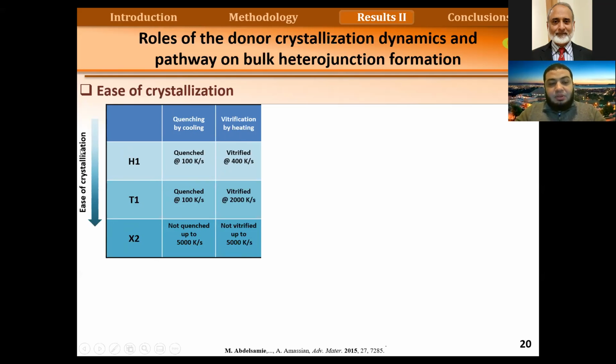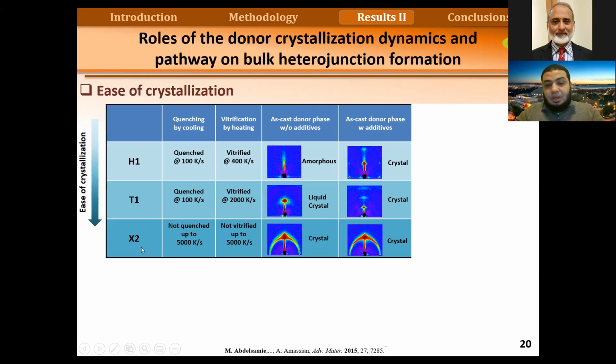We can see on the left here that the ease of crystallization changes from H1 to T1 to X2. When we make a film, for H1, because it can be vitrified very easily, it forms an amorphous compound without additives. The second one forms a weakly ordered liquid crystalline phase, and the third one forms a crystalline phase without additives. If we use additives, we can form a crystalline phase for all of them. But for the first two materials, we need the additives to get high efficiency, while for the third one, we don't need the additives.